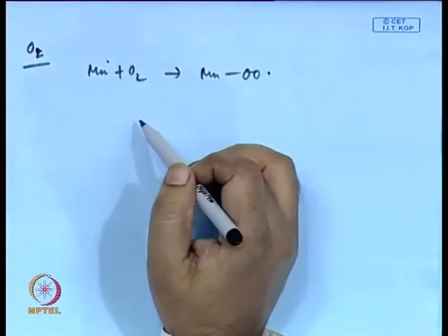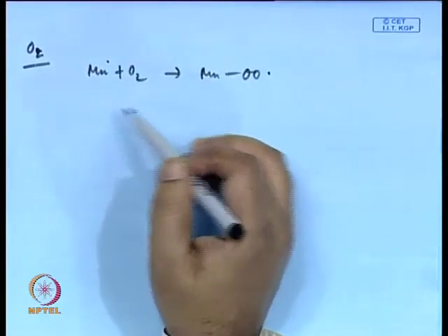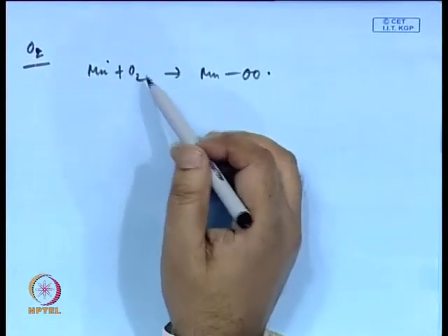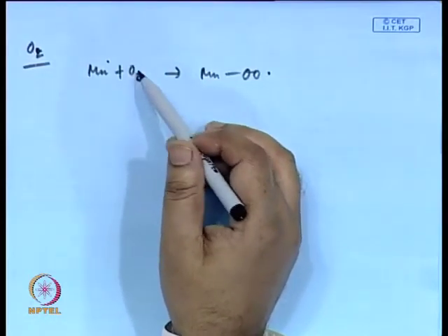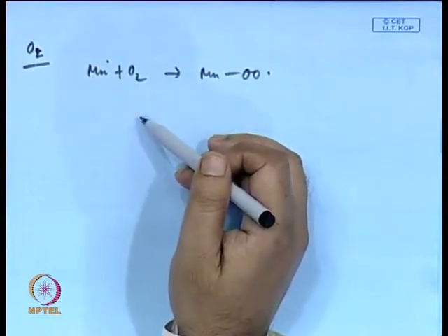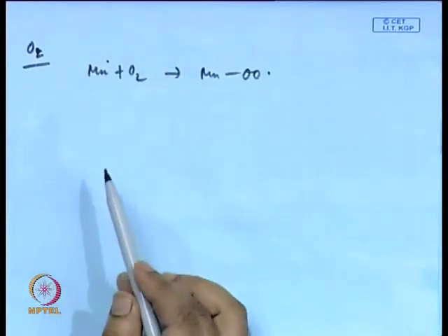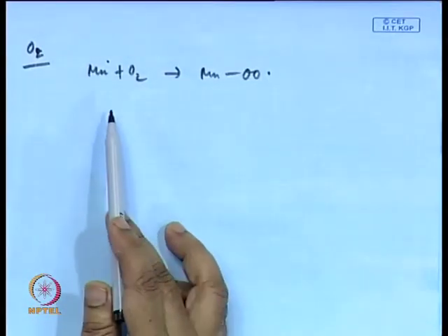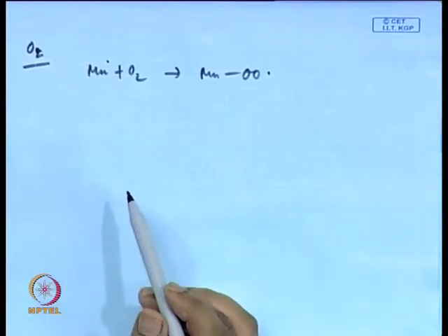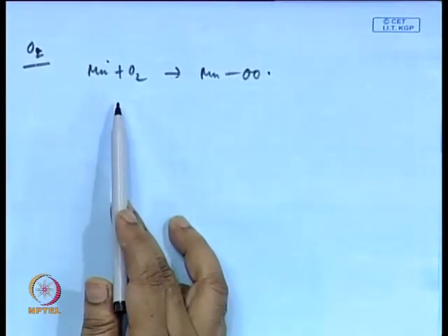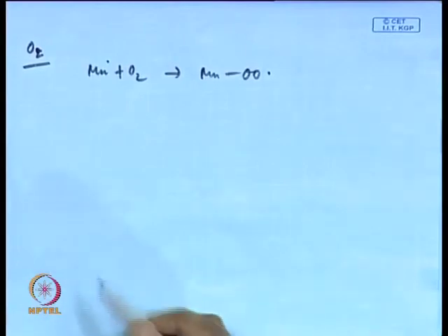So, which means that when you do chain polymerization reactions, radical chain polymerization, you must remove the oxygen molecule from the reaction medium as much as possible to avoid this killing of the propagating radical, by which it will stop the reaction and also reduce the molecular weight. So, we have now learned transfer reaction and initiator inhibition reaction and retardation reaction as well.